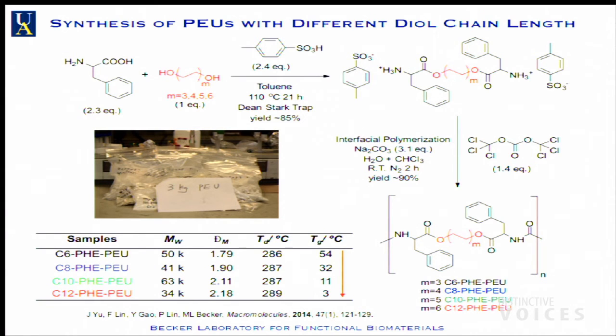Now the interesting thing, and this won't be obvious to this crowd, but I'll point it out because it's something the materials companies often miss, is that TD is called the degradation temperature. When the degradation temperature is 200 degrees above the glass transition and 150 degrees above the melt, you don't need any solvent to process it, so it can be injection molded and processed in traditional ways. When you're taking a material through the regulatory process, the 2 most expensive things to prove, and where most things die, are these: the first thing the FDA will ask is how much residual metal, how many parts per million. The second question is how many parts per million solvent. Those are really difficult when you're making large batches.